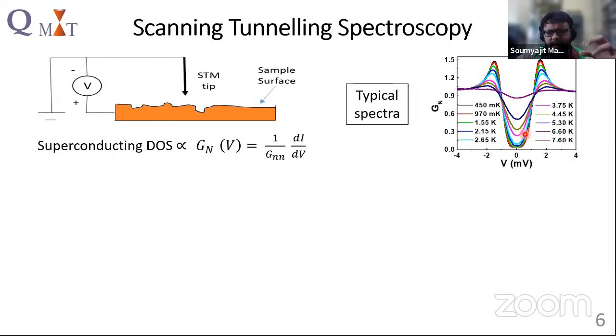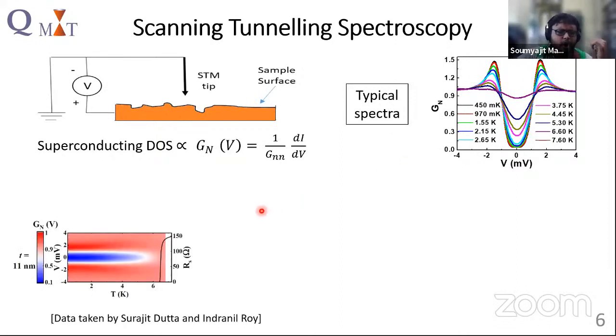We have converted these types of graphs to an intensity plot of this conductance spectra, where the x-axis is the temperature. Here you can see the blue line is the gap. This is the 11 nanometer sample, and along with the spectra we have also plotted the R versus T. As you can see, the gap vanishes at almost the same temperature where the resistance vanishes in the R versus T plot.